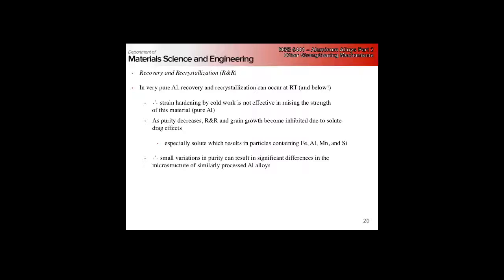Okay, yeah, right? Yeah, except here we're talking about grain boundary, right? So we have solute atoms that are going to segregate preferentially to the grain boundary because that's a low energy configuration, right? So now if I can maintain a low energy by keeping solute atoms preferentially at the grain boundary, and I go to move my grain boundary by thermal force, what's going to happen?